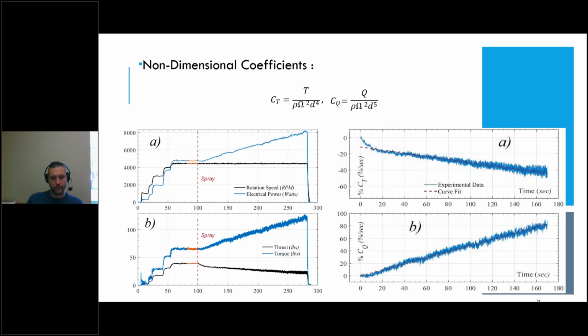So during testing, we record different parameters like the rotational speed, electrical power, the thrust, and torque. And during a test, what we do basically is we start the rotor, we slowly increase the RPM until we reach the target RPM for the test. And then, as you see on the plots, we initiate the icing spray in the cold chamber, and then ice accumulation begins on the rotating blades. So as you can see, because the testing is done at a fixed rotation speed, so at fixed RPM, the electrical power will increase due to the ice accumulation on the blade.